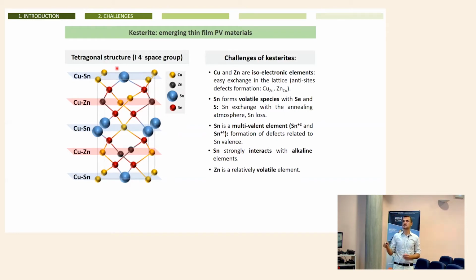In addition, tin tends to form volatile species with the chalcogen, with selenium and sulfur. So the control of tin in this structure is very complex, extremely complex. Tin, in addition, is a multivalent element. So you can have tin plus 2, tin plus 4, or even in this solid state structure, tin plus 3 or something like that can also be possible. So this kind of multivalent element tends to form defects in the band gap. Normally, these defects are detrimental for the solar cell performance.